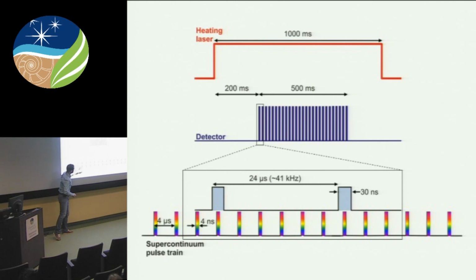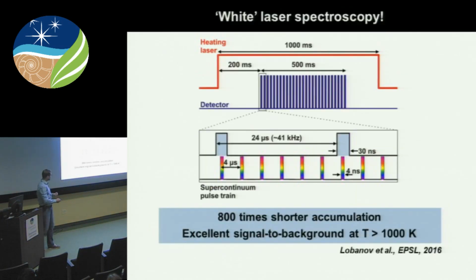So we take an electrical output of one of the pulses as a trigger for the heating laser. We heat our samples for just 1 second. And 200 milliseconds into the laser heating pulse, we start opening the detector, our gated detector. And we do it in such a way that the gates of this detector overlap exactly over one of our supercontinuum pulses. And we do that for half a second. As you can see, 500 milliseconds is half a second. So we collect a bunch of supercontinuum pulses in just one collection, in just 1 second.